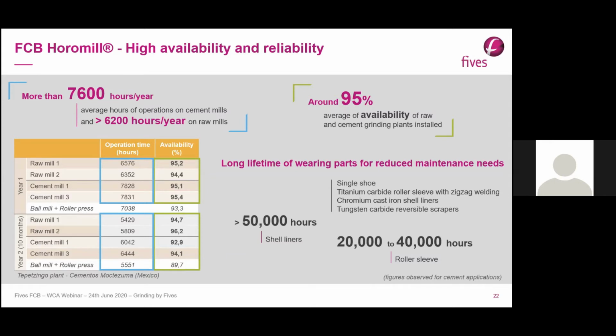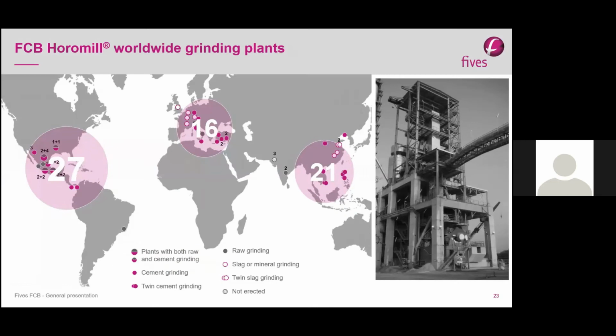The average availability is around 95% of the whole plant. Combined with a long lifetime of the wear parts and spare parts, that permits to reduce maintenance needs and maintenance costs and so on. We have more than 50,000 hours of operation for the shell liner, for instance. And the roller sleeve can last more than 20,000 hours of operation, typically between 20 to 40,000 hours, depending on the abrasiveness of the product and on the maintenance need.